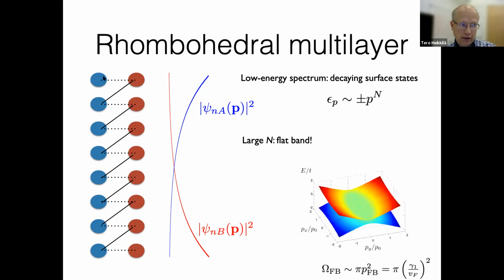What you find out is that at p equal to 0, at the Dirac point, there are two uncoupled sides. This blue one here on the top and the red one on the bottom are localized states at p equal to 0. And once you put a finite momentum away from the Dirac point, you induce some non-localization for these systems. It's the overlap energy between these two eigenstates that provides a finite dispersion in this system.